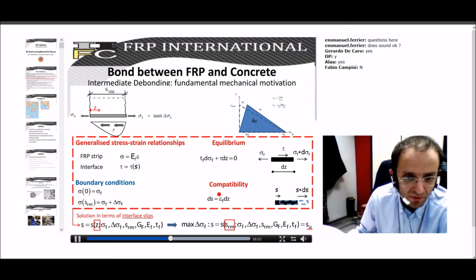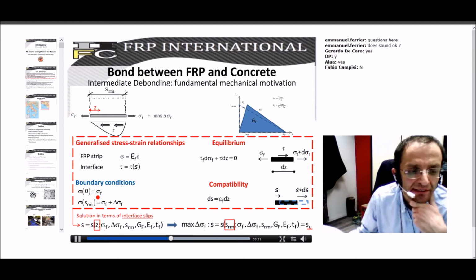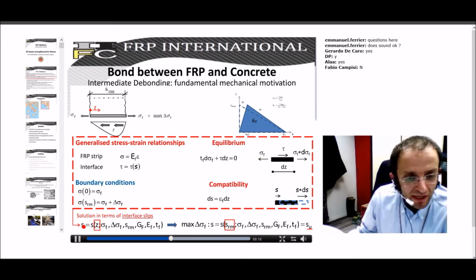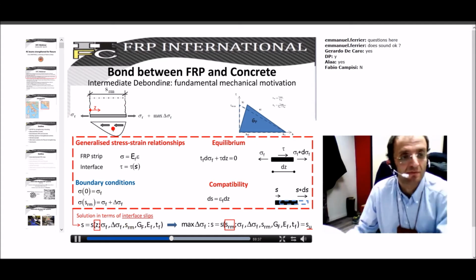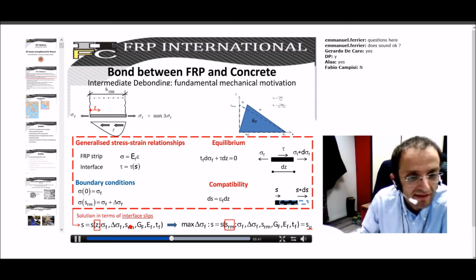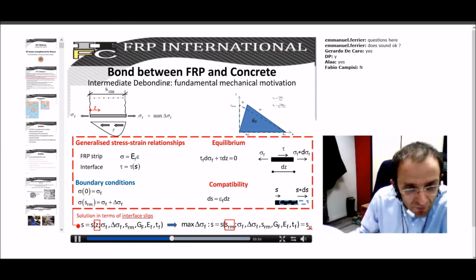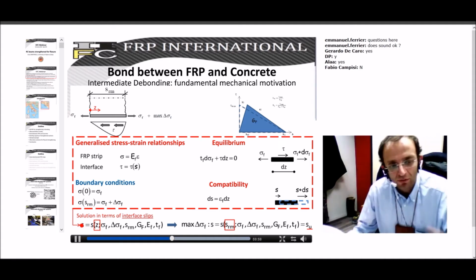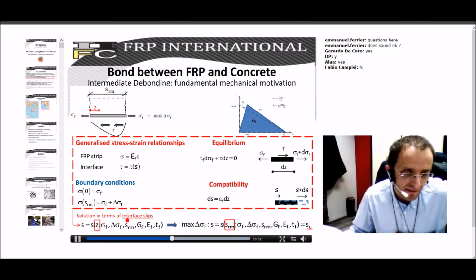But we have a differential problem with some boundary conditions. For instance, here I wrote these conditions explicitly in terms of sigma. If you solve this problem, you can obtain the value of the slips across these interfaces, depending on z, the position, and depending on the initial value of sigma and the final value of sigma, or in other words, depending on the increase. Of course, also the actual distance between cracks is an important parameter, and it goes without saying that the problem is also governed by the fracture energy of the interface and by some key parameters of the glued member. Usually this is not possible in an analytic way, but you can do it numerically. If you can write this equation, you can also solve it.